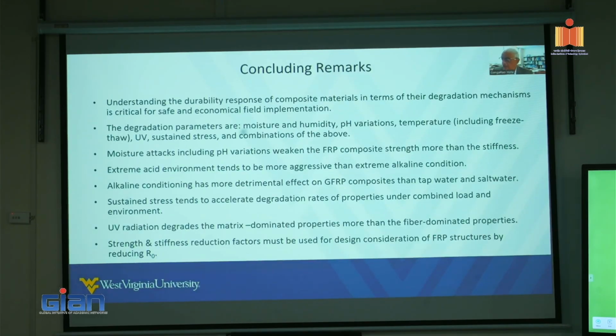In conclusion on the durability issue, I must say that understanding the durability response in terms of degradation mechanism is critical for safe and economical field implementation. These degradation factors have already been touched upon by Dr. Gupta a few minutes earlier. Moisture attacks, including pH variation, weaken the FRP composite strength more so than the stiffness aspect of the composite, because the stiffness is a function primarily of the fibers rather than the resin. Extreme acid environments tend to be more aggressive than extreme alkaline conditions. That is because the resin gets more affected than the fiber under acidic conditions.